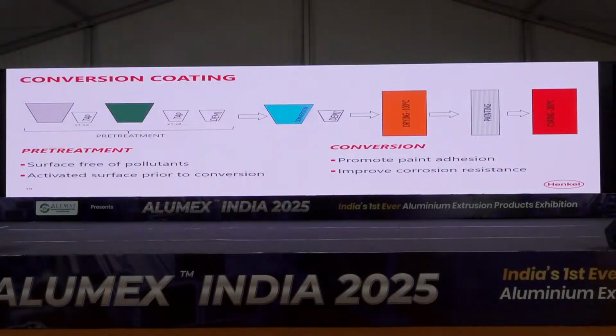Of course, all our pretreatments in conversion can be applied by immersion, by spray, or by cascade. So these are the typical different lines that we can find in a conversion pretreatment. For the pretreatment, the target is to clean the material and leave it free of any kind of pollutants, and activate the surface in order to later give the right conversion layer. So we will do this through an acid, or through an alkaline plus acid, depending on the customer, in order to keep the surface as clean as possible for the conversion.